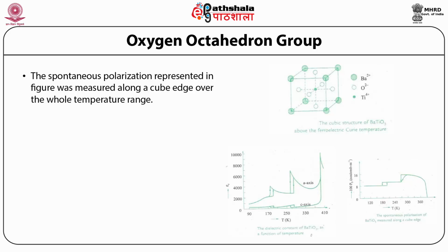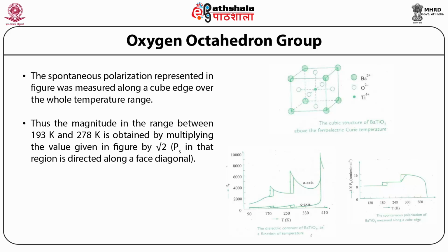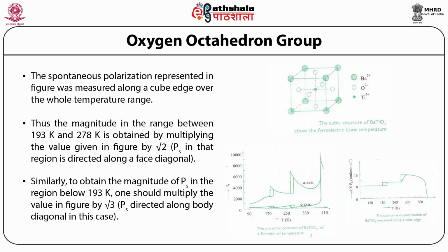The spontaneous polarization represented in the figure was measured along a cube edge over the whole temperature range. Thus, the magnitude in the range between 193 Kelvin and 278 Kelvin is obtained by multiplying the value given in the figure by root 2. PS in that region is directed along a face diagonal. Similarly, to obtain the magnitude of PS in the region below 193 Kelvin, one should multiply the value in the figure by root 3. PS is directed along a body diagonal in this case.